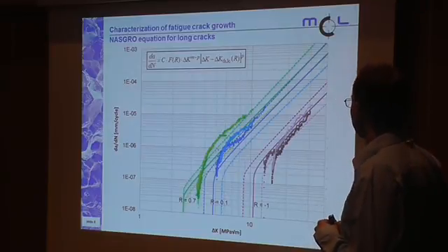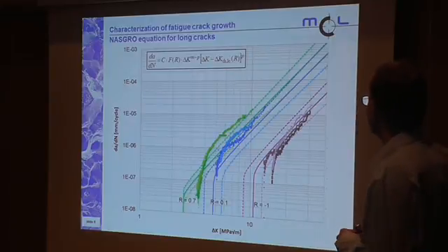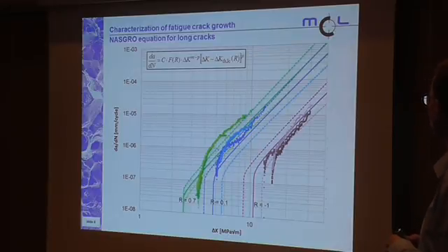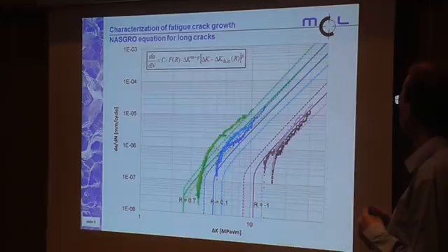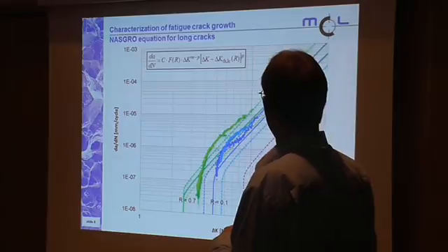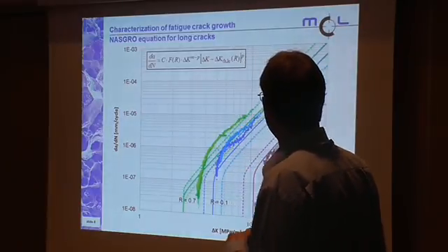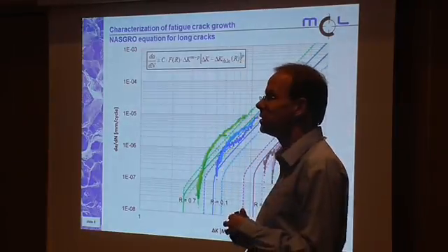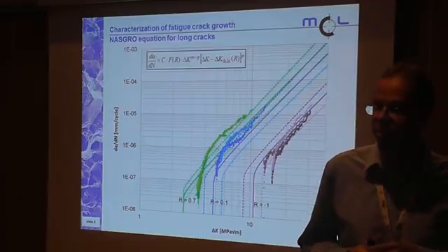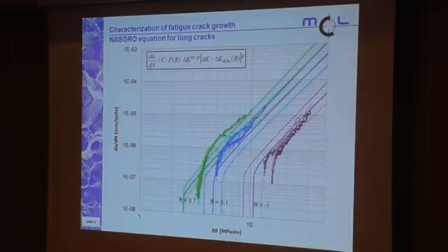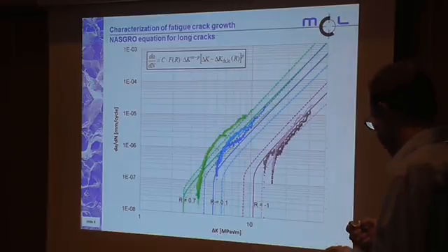With that, we can proceed to evaluate our crack growth measurements, which we have done at 3 different R ratios: for a crack that should be fully open at the load ratio of 0.7, and then for the 2 load ratios of 0.1 and -1. What you see, and we can fit the parameters of the NASGRO equation, which is of course the constant C, the slope of the Paris region m, and the parameter p that controls the near threshold region. And of course also for that one we can get a statistical estimate of the parameters and the confidence intervals for those parameters.